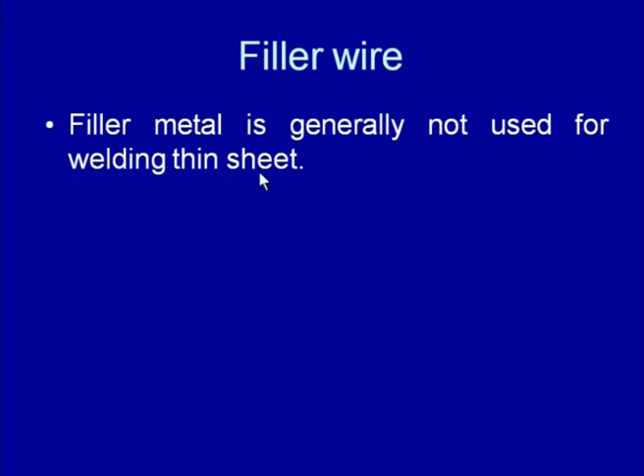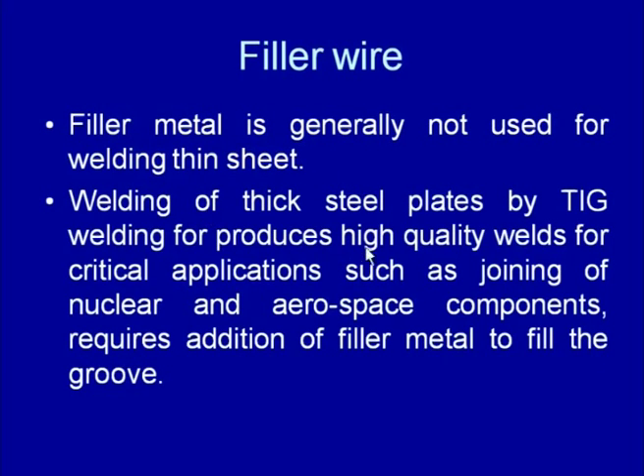Apart from the shielding gas, we commonly use filler material for filling in the gap between the base materials to be joined. The filler material will be used in light of the base materials and the kind of weld geometry being used for developing a weld joint. The filler material normally is not used when welding thin sheets, like 1 mm thick sheet, which is welded by directly melting the edges of the plates and allowing them to solidify to obtain metallic continuity. But when thick sheets and thick plates are welded by the GTAW process, filler materials in the form of rods are invariably used, and this is commonly done in the case of nuclear and aerospace components.